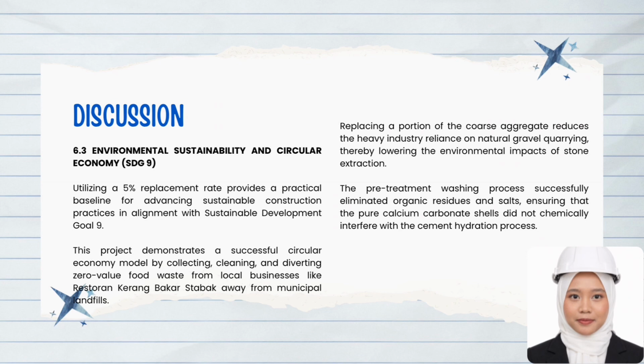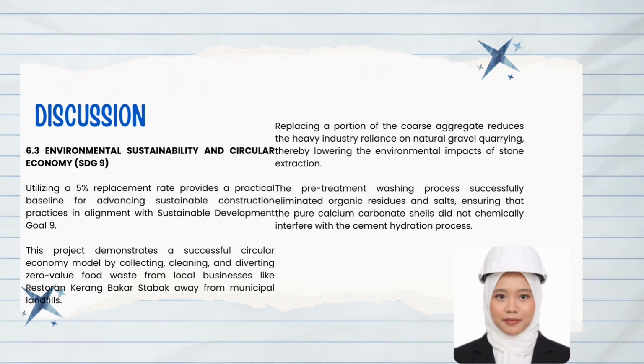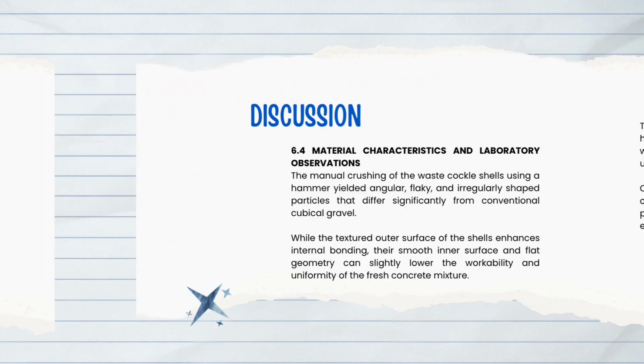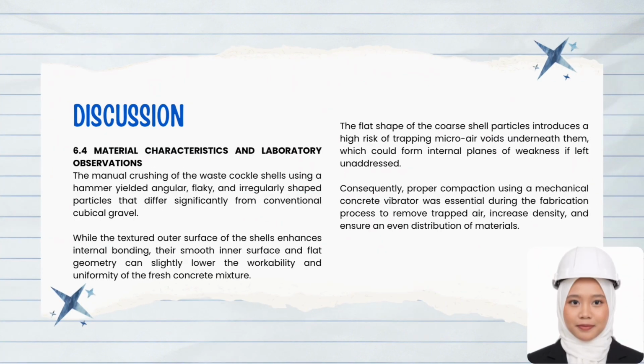Aligning with SDG 9, this project promotes a circular economy by upcycling zero-value food waste from local businesses like Restoran Kerang Bakar Stabak, preventing it from entering landfills. Furthermore, replacing 5% of natural gravel directly reduces the ecological impact, energy use, and carbon emission associated with stone quarrying and material transport. Finally, our laboratory observations show that manually crushing the shells with a hammer produces angular and flaky particles, while the textured surface improves bonding, the flat geometry creates a risk of trapping micro air voids underneath.